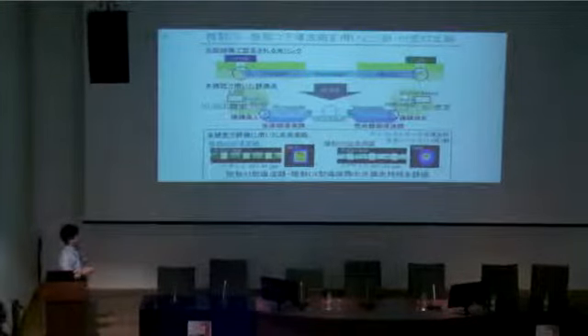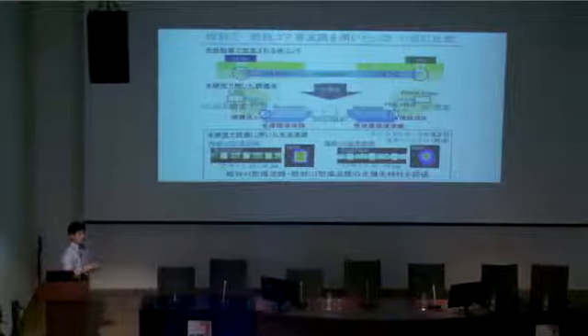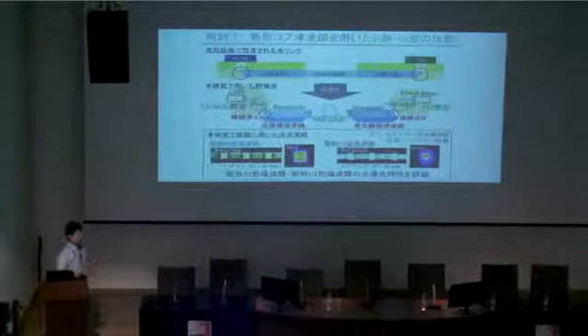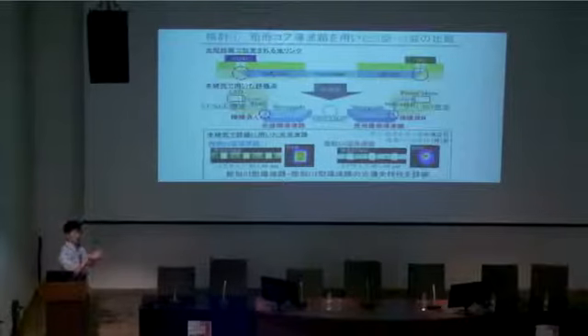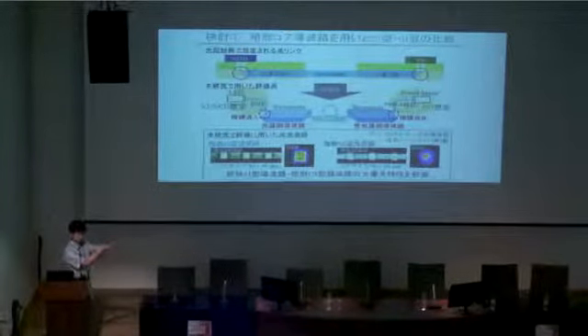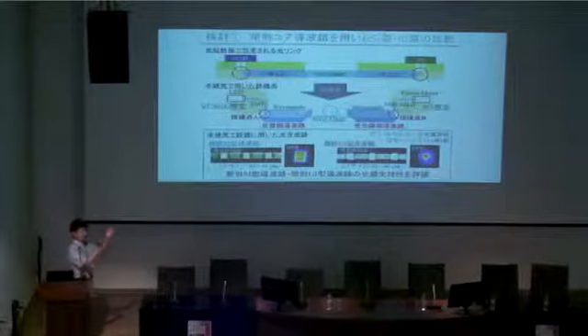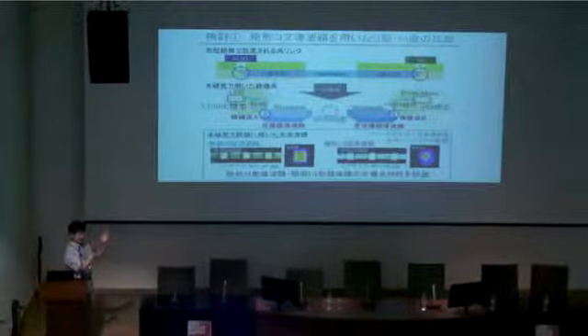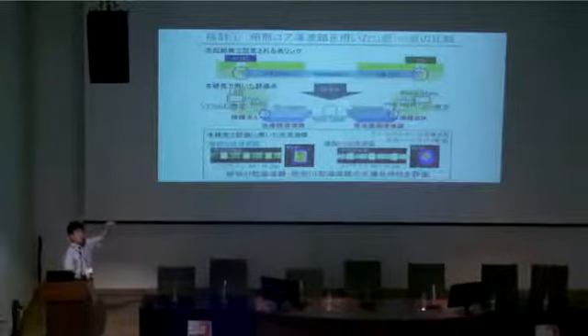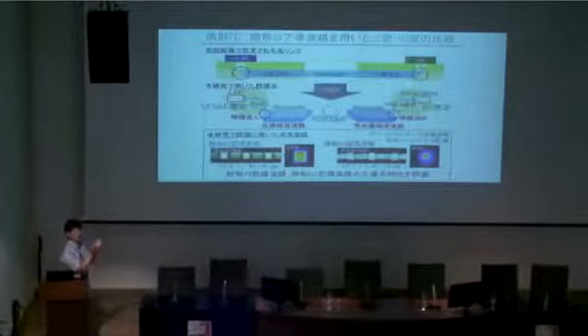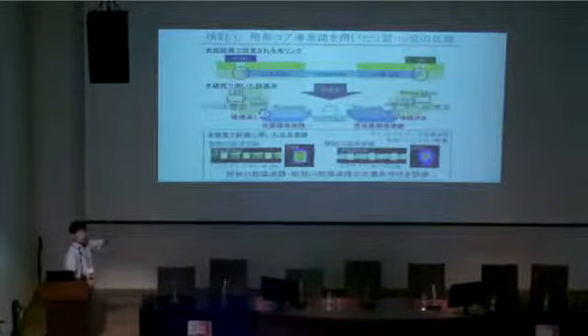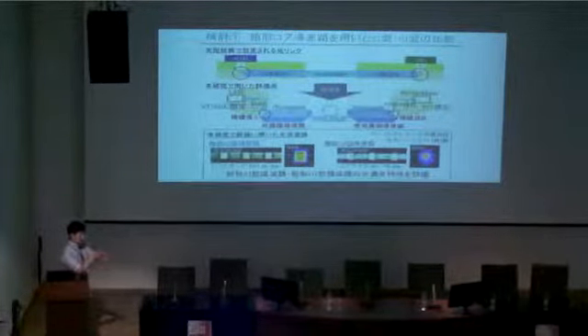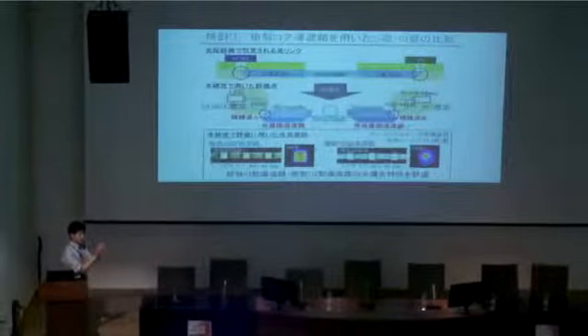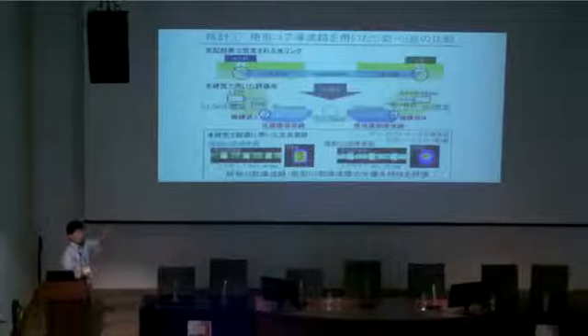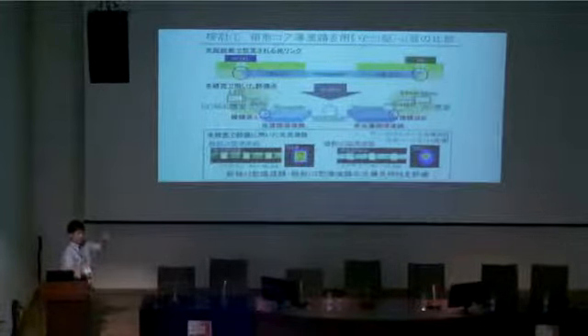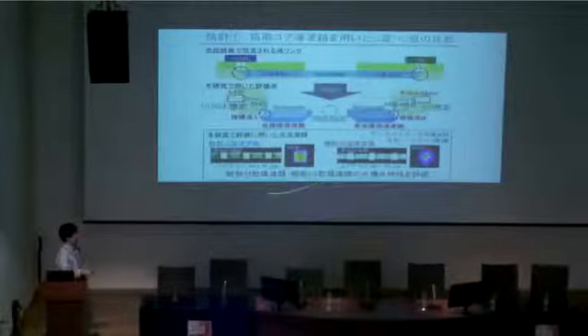And this is particularly for the mirror. At the end of the 45-degree mirror, if the light is completely broadened to the whole core area, it spreads out after the mirror. Then if the small photodetector is waiting, some light is not coming into the photodetector. While in the case of graded index, the light is well confined. So even if slightly diffracted from the mirror, it can go into the small photodetector. That is what this slide is showing.